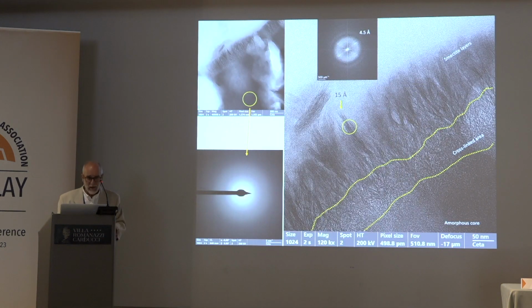This is an ultra-thin section. So it's similar to the previous picture, but now we have here the structure. You see the amorphous core is a reticular area. It's amorphous, so this electron diffraction is from this fiber. So we don't see anything, or the crystallinity is extremely low.